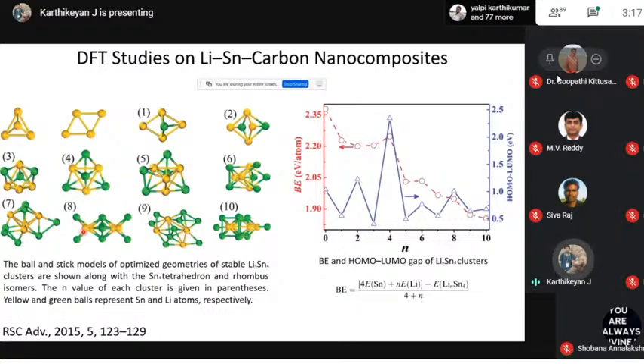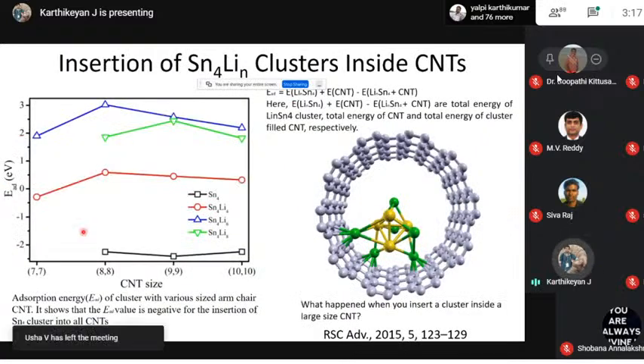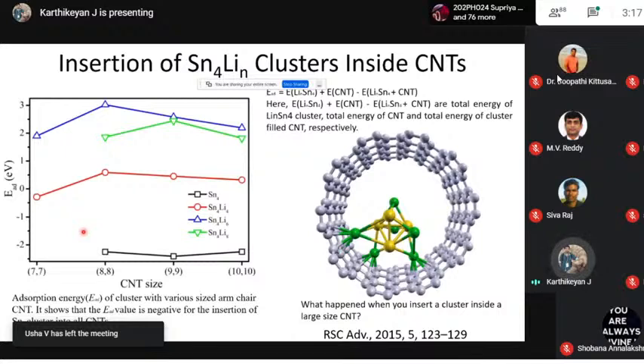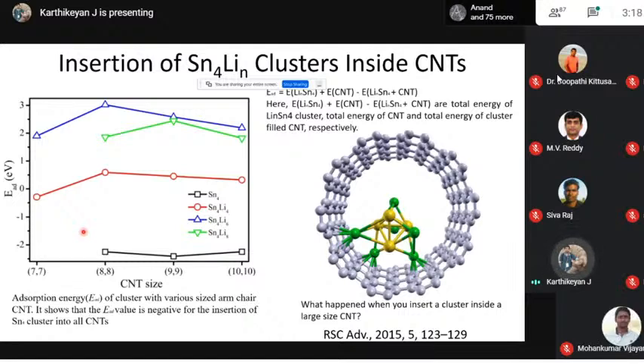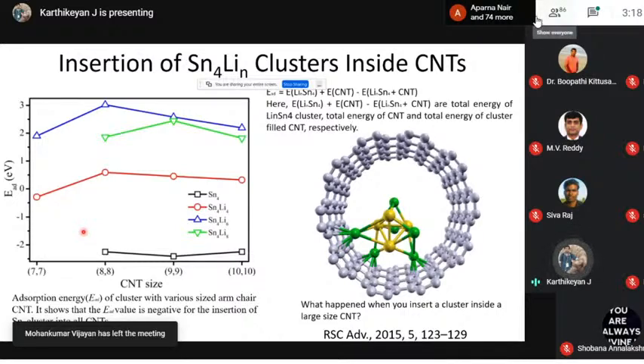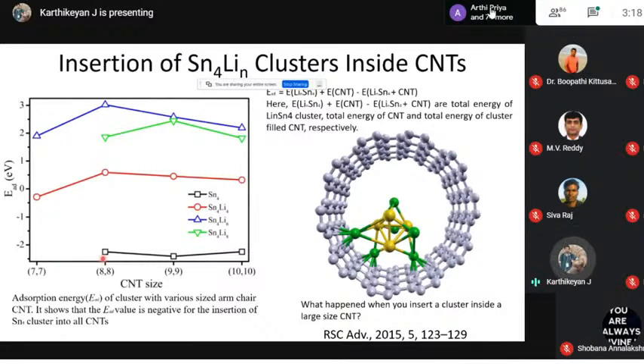So we are going to use these lithiated tin clusters and put them inside the CNT. We want to understand the composite of tin-lithium alloys inside CNT. When you grow this material, the cluster size will be controlled by the CNT chosen for the experiment. But since we are doing this theoretically, we first have to find the proper CNT size for inserting these clusters. So this is the adsorption energy. We calculated the adsorption energy for various tin clusters, varying the lithium numbers, and filled these clusters inside various sizes of CNT.